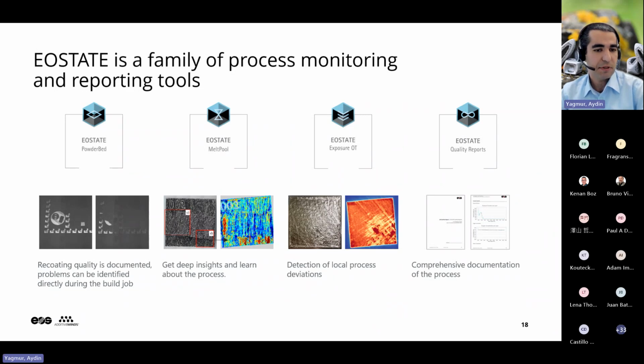Then we have a melt pool system. It is a photodiode that collects the backscattered laser beam in the visible spectrum and near infrared wavelength spectrum, which gives insights from the melt pool, as the name indicates. The next system is Eostate Exposure OT, which is a unique solution in the market. It is a camera taking pictures of the whole build plate during the layer time and gives us long exposure information of the powder bed, not only during melting, but also after melting. We can see the whole build plate with Eostate Exposure OT.